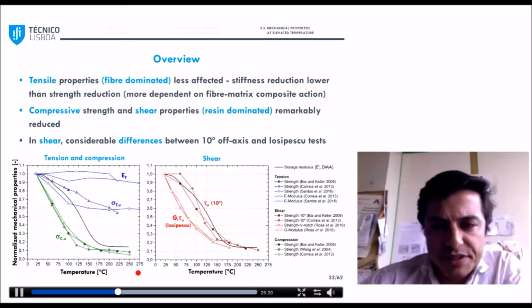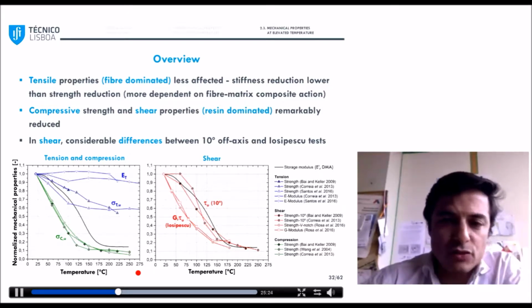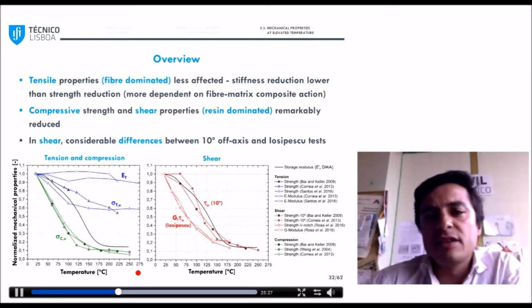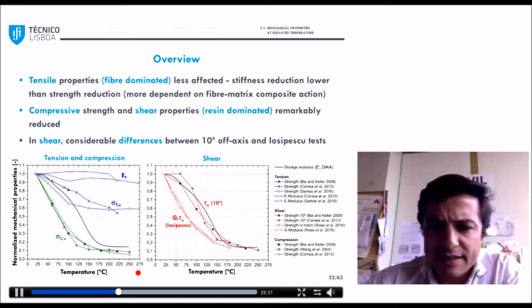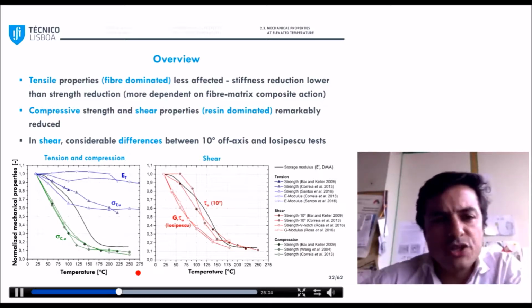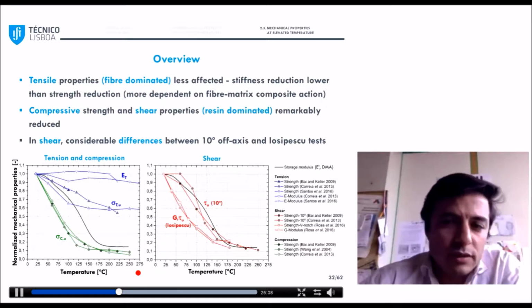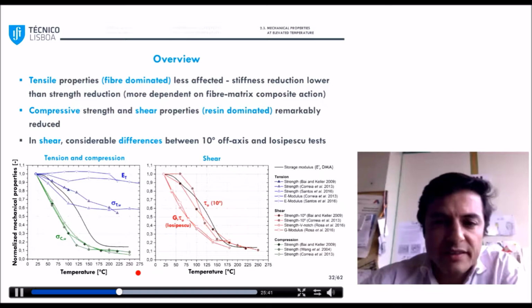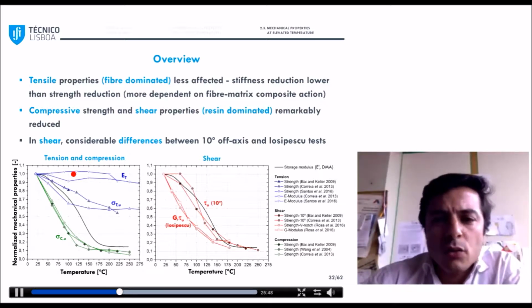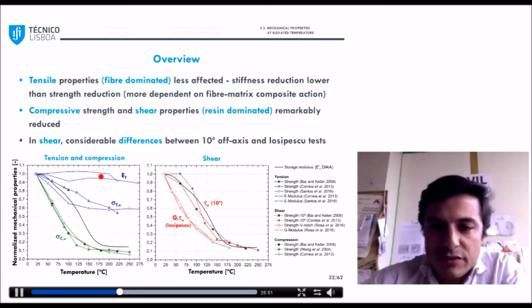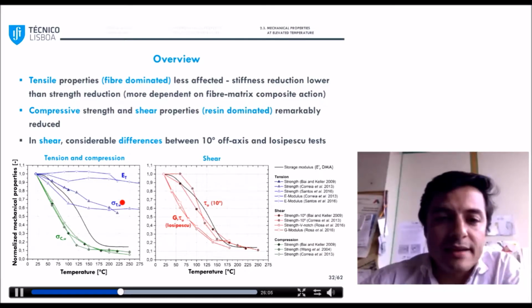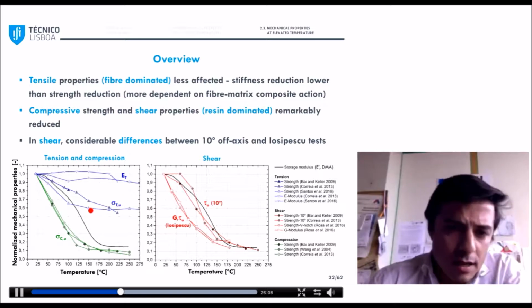These figures show the mechanical properties as a function of temperature, normalized to room temperature, obtained in this study and also by other colleagues. So I would highlight, first of all, the tensile properties, which are shown in blue, and as you may know, these properties are fiber dominated. So tensile properties are the least affected for this reason, especially the modulus, which suffers very little reduction for this temperature range. On the other hand, the tensile strength, which is shown here, is more affected than the modulus because the resin is no longer able to distribute evenly the stresses among the fibers.